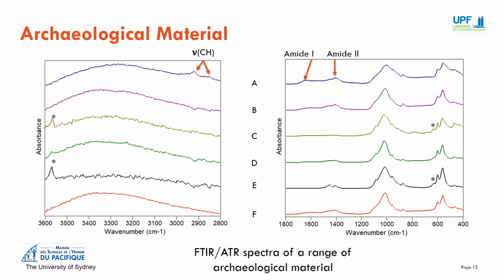This slide presents the FTIR-ATR data collected from a range of archaeological material. Examination of the spectra collected from samples in C and E reveal the presence of bands at 3,570 and 630 wave numbers, marked by the asterisks, indicating that these samples were subjected to temperatures of at least 700 degrees Celsius. In spectrum A, there are 2 bands at 2,919 and 2,849 wave numbers, which are CH stretching bands assigned to lipids and proteins.